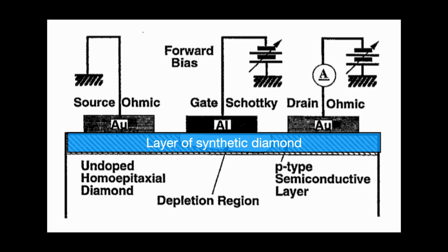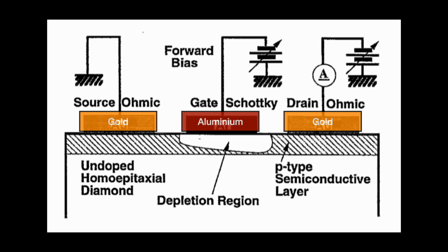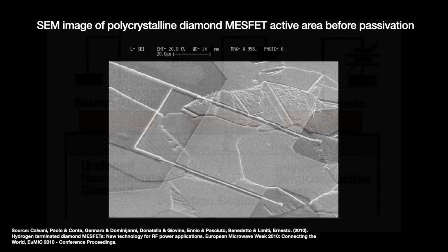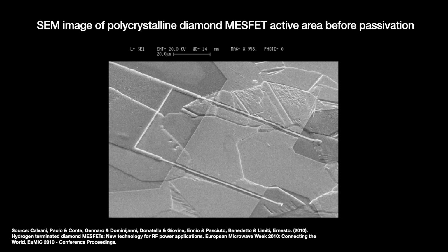Then, two pieces of gold are deposited on top to serve as the source and drain. In between, we have an aluminum gate. You end up with a working MESFET, albeit working rather quirkily and with slower charge carriers. Over the years, more MESFETs and variants have been made with modifications added for improvement, like hydrogen termination being replaced with oxygen termination, which is more stable in air.